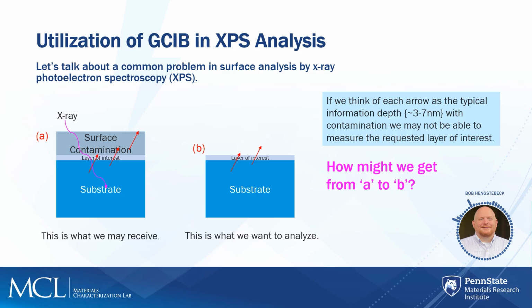And so it's not rare to have these surface layers, such as shown in the example A, be greater than our information depth. And when that happens, the photoelectrons that we're generating with an X-ray source, which can go quite deep into the material, don't have enough energy to escape so that we can detect them. And if there's a layer of interest we want to see, we want the sample to look more like B. And the question becomes, how can we clean the sample without changing the chemistry of the surface and remove that surface contamination? There aren't a lot of great methods.